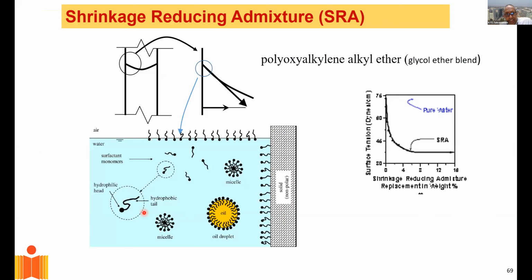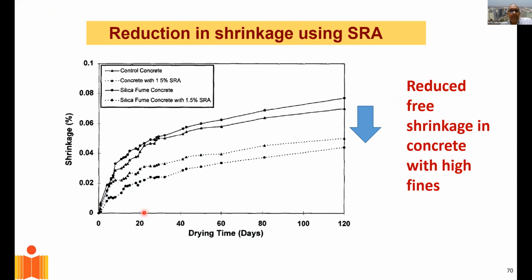One of them is called the shrinkage reducing admixture, which is basically a surfactant. And what it does is that it basically reduces shrinkage. So this is the shrinkage that I measure from concrete, which is densified. But the minute I add a little bit of SRA, which is 1.5% of shrinkage reducing admixture into concrete, you can see the shrinkage decreases tremendously. So we are now able to produce these admixtures that help us control the shrinkage.